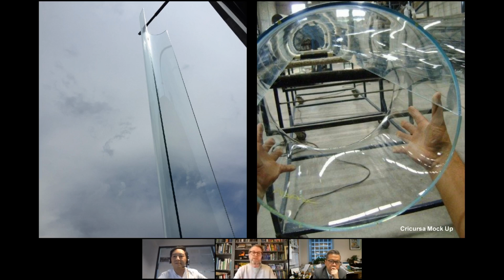So getting that consistent quality, and also bearing in mind that we intended to laminate these half tubes. So that means taking two tubes and nestling them into each other, slightly different radii. In order to do that, it's very important that the surface quality of that glass was consistent, so that the lamination process would be successful.